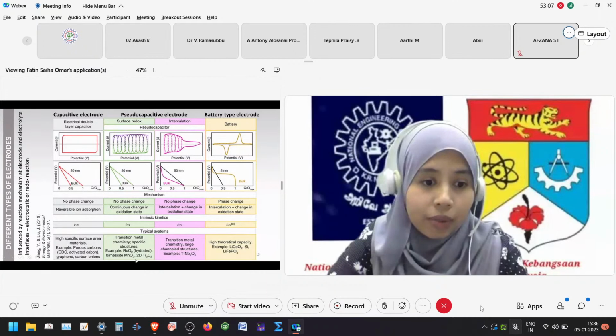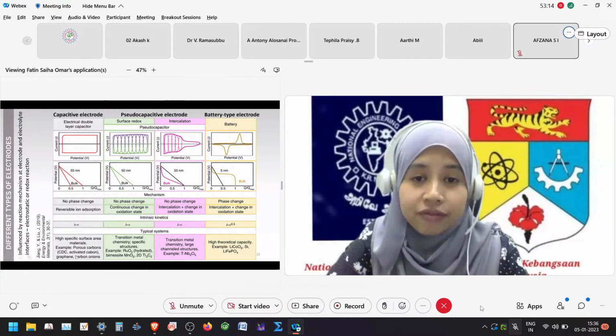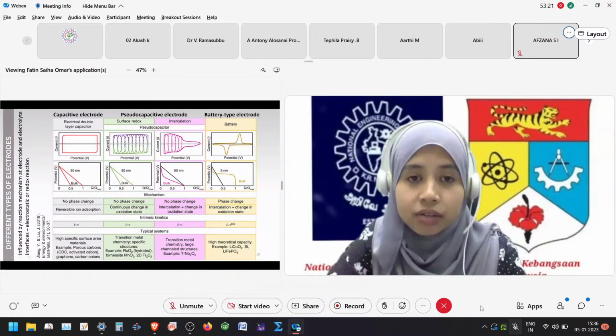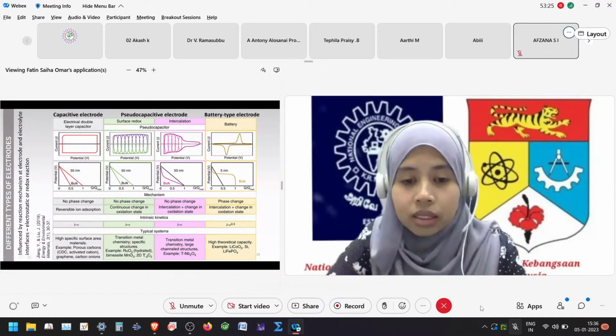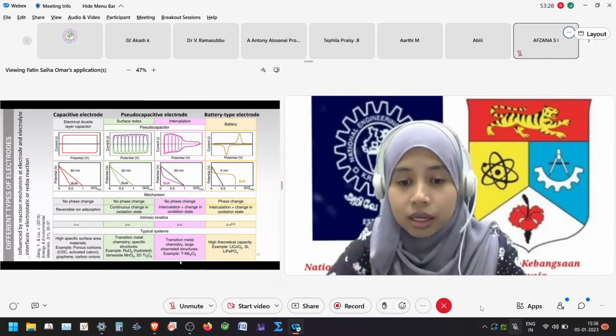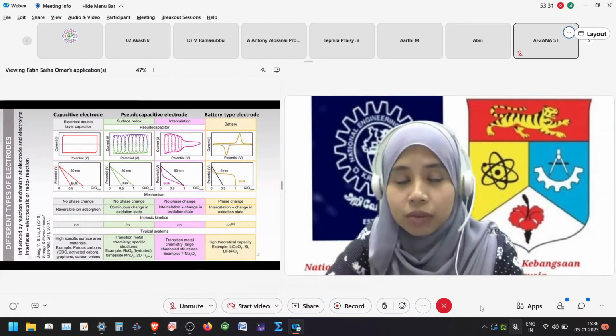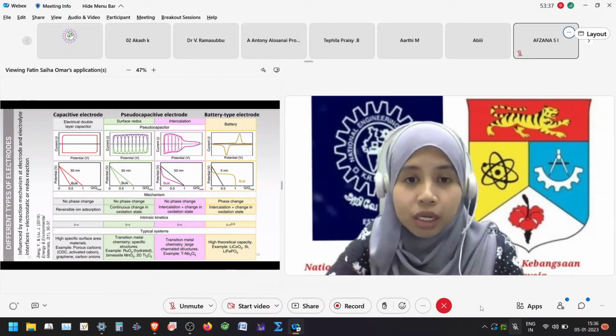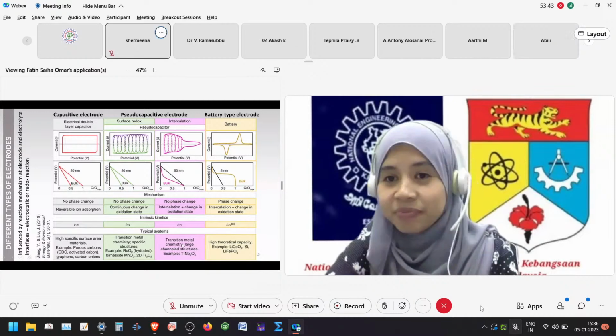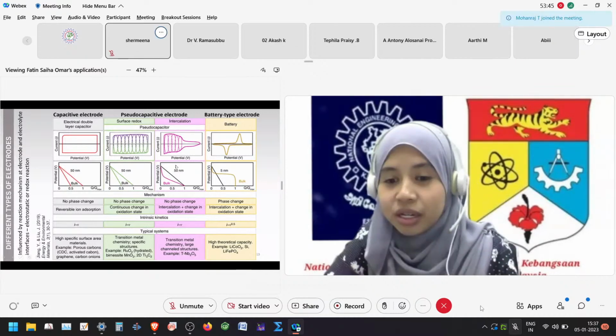Like capacitive electrodes, typically they use CNT, activated carbon, graphene. Okay? And for pseudocapacitive electrodes, for surface redox, use ruthenium oxide, manganese oxide, titanium carbide. And for the intercalation, niobium pentoxide. So it means that the pseudocapacitive electrode really depends on the material of the substrate and the material coated onto the substrate. Then battery type electrodes, previously shown, lithium cobalt oxide, lithium iron phosphate, and so on.